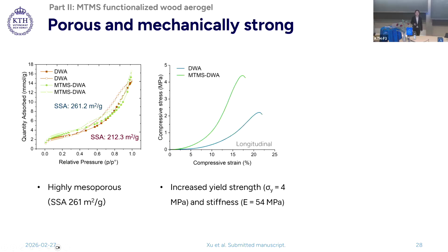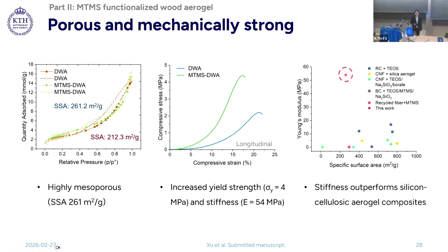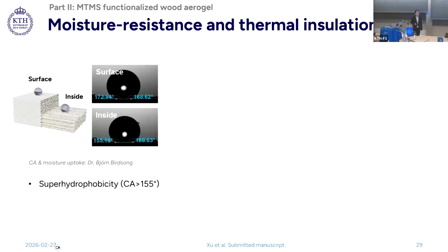MTMS condensation improves the mechanical properties of wood aerogel, evidenced by the increased yield strength and stiffness. The stiffness outperforms the reported silica cellulosic aerogel composites due to the oriented cellular structure of wood and the aligned cellulose microfibrils within the cell wall. Additionally, the contact angle on the inner part of the sample exceeds 155 degrees, while those on the surface reach up to 170, indicating the superhydrophobicity as well as the effective coating throughout the volume.